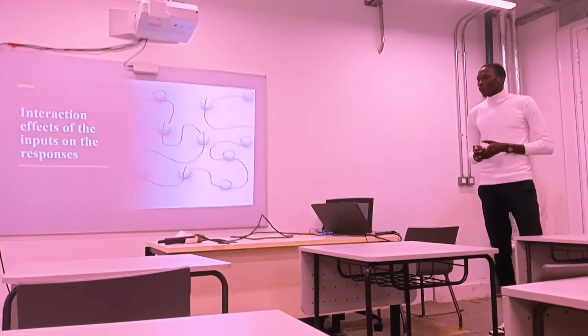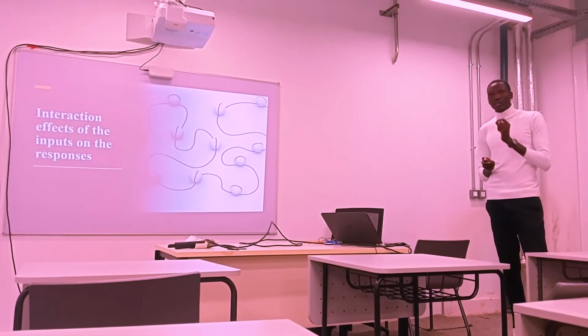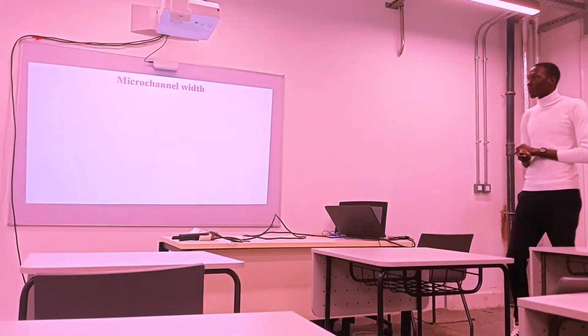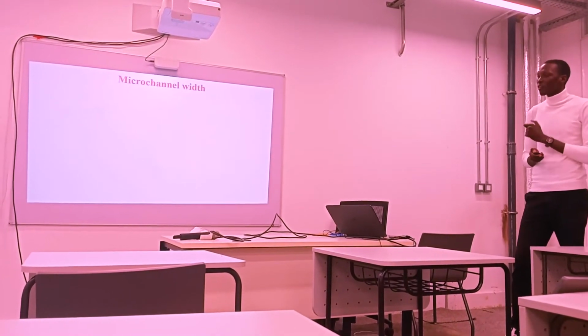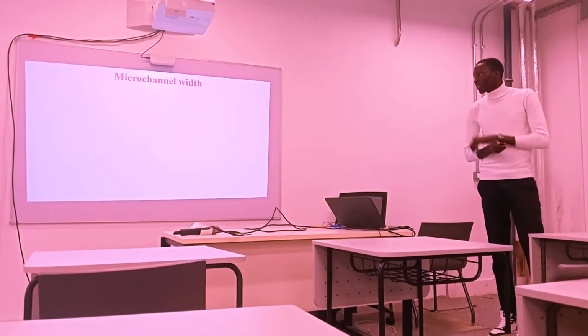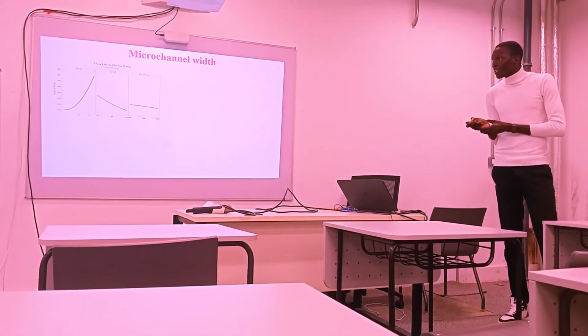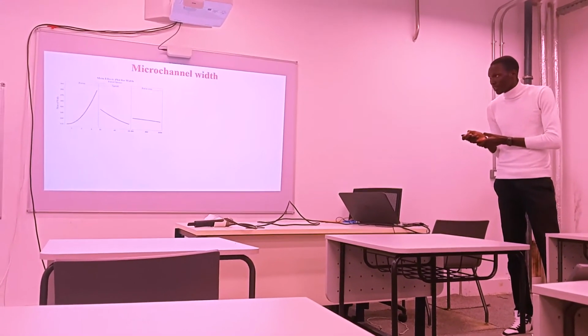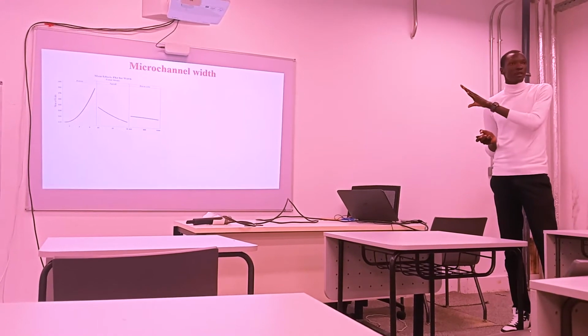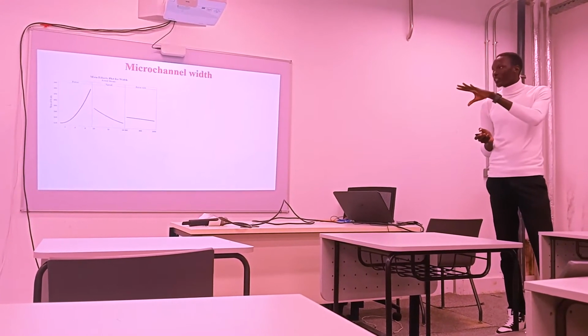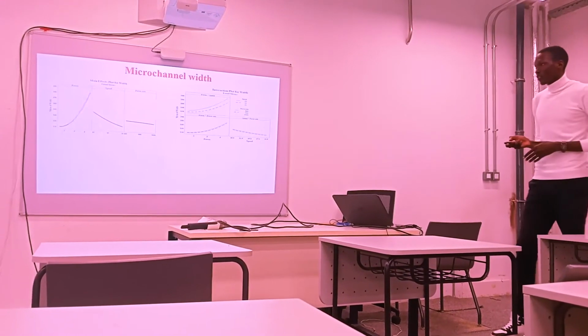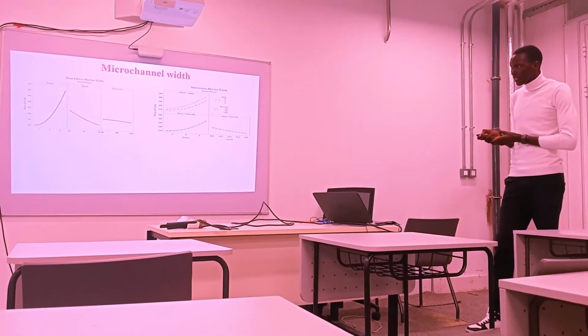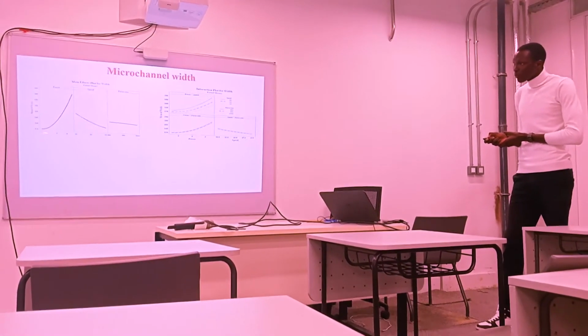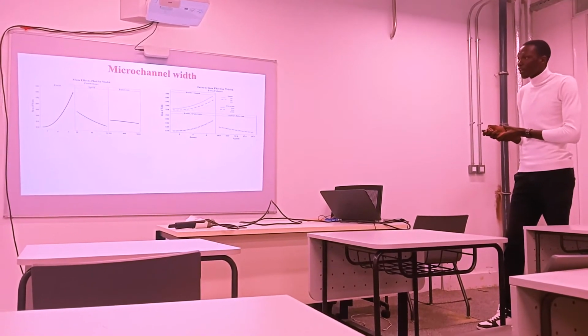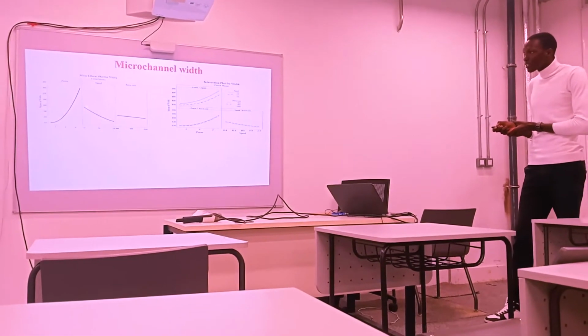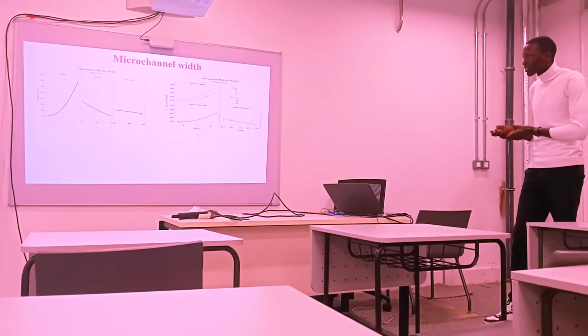So, we then studied the interaction effects of the inputs on the responses. Following the results we got using the response surface methodology, we start with the microchannel width. This is the main effects plot for the width. Now, these results simply confirm the results we got in part 1. There's nothing new here. So, from this graph, we can see that microchannel width increases with the increase in power, but decreases with the increase in speed and the pulse rate.